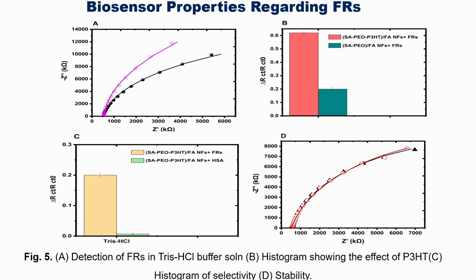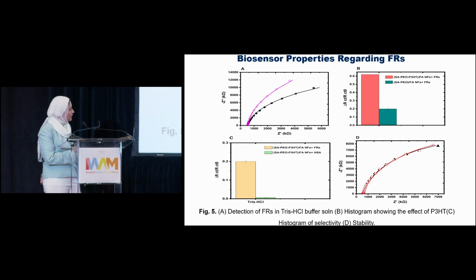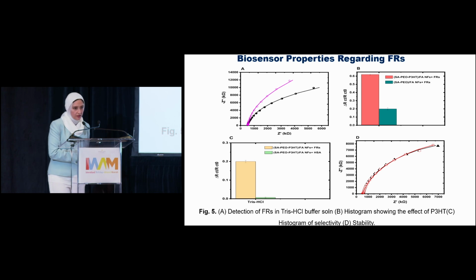Here, this histogram shows the difference between the performance of our biosensor with P3HT and without P3HT. As we see, there is a significant difference, which confirms the additive effect of our conjugated polymer. Here, we examined the selectivity using another interfering plasma protein, human serum albumin, and there is a significant difference, which confirmed the higher selectivity.